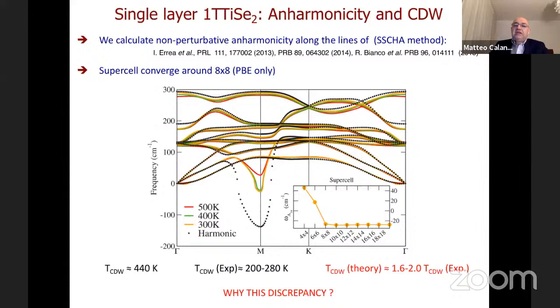What happens if you do much larger supercells? So we did very large supercells, up to 8x8, 10x10, and so on. And the system converges around 8x8. So 8x8 is 64 times 3 atoms, so it's a substantially big supercell. And what happens is that the anharmonic correction is the main player. Namely, you start from a harmonic phonon dispersion that is strongly imaginary. But then when you increase the temperature, the anharmonicity pushes up the phonons a lot, as you can see, for different temperatures, and removes the instability.